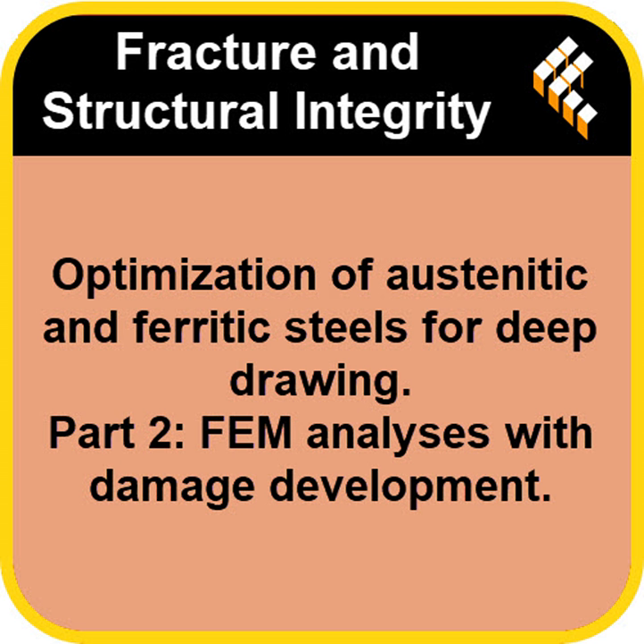Got it. So let's talk materials. This research compared two very common stainless steels, AISI 304 and AISI 430. One's austenitic, one's ferritic. What's the difference in practice? Well, the tensile test showed some clear differences. Interestingly, the AISI 430, the ferritic one, actually had a higher yield strength. Higher yield strength, so it takes more force to start permanently deforming it. Around 340 MPa versus 267 for the 304. Correct. About 340 MPa average for 430 versus 267 for 304.